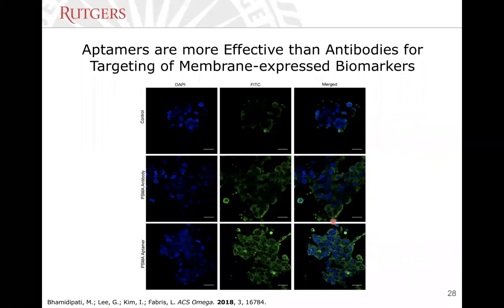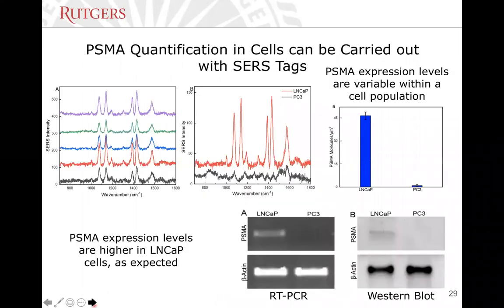And not only did we find out that it works, but if we look at this particular middle section, where we have functionalized both the aptamer and the antibody with FITC, and we monitor the presence of FITC fluorescence on these cells, we see that comparing PSMA antibody stained cells and PSMA aptamer stained cells, for the same cell population, we see a substantially more fluorescent signal from the PSMA aptamer. So we not only find that it works, but it does work very well. And so we were assured that this was doable.